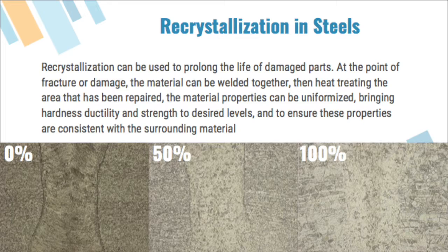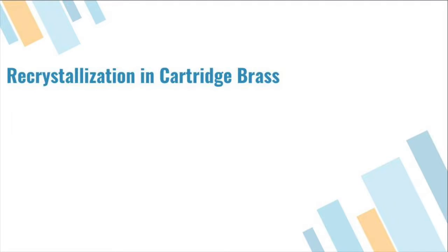By annealing the heat affected zone, the material properties can be fine-tuned and be made consistent with the rest of the part. These 3 images along the bottom show a laser seam welded S30403 stainless steel. And on the left shows 0% recrystallization, in the center 50% recrystallization, and on the right total recrystallization. The rest of this presentation will deal primarily with the recrystallization of C260 brass, commonly referred to as yellow brass or cartridge brass, composed of 70% copper and 30% zinc.